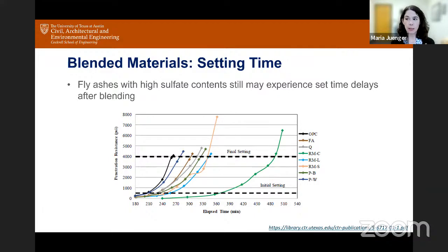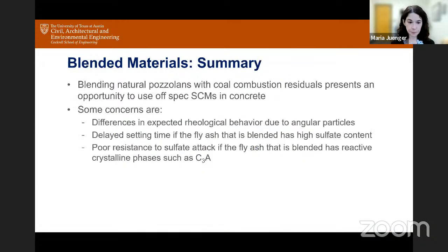And so it complicates our need to characterize these materials and understand them better. We can't just use our current specifications that are based completely on oxides. We have to be a little more careful, and maybe it requires that we do X-ray diffraction to look at the type of sulfate that's in the system, to look at the type of C3A that's in the system. Because once we start blending, we have a lot more unknowns, and a difference in the way things behave than the way they were originally.